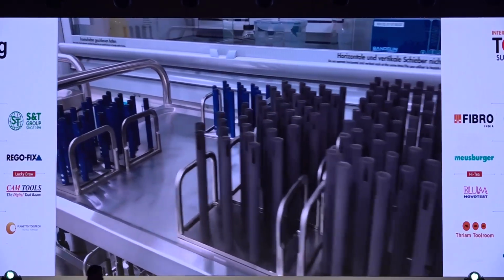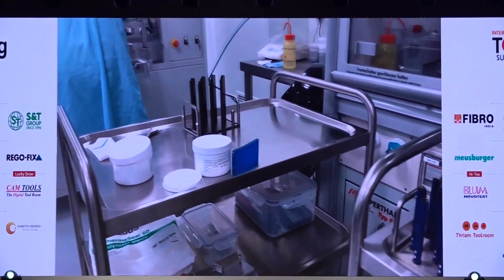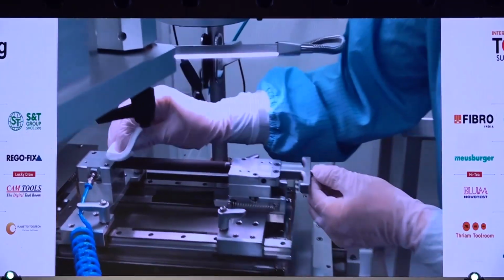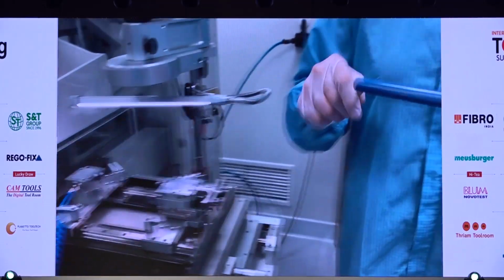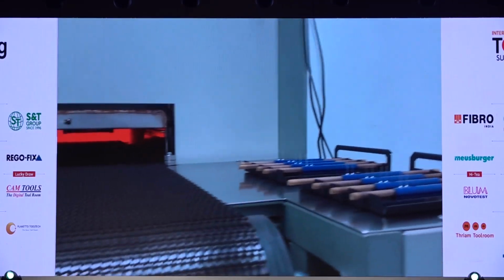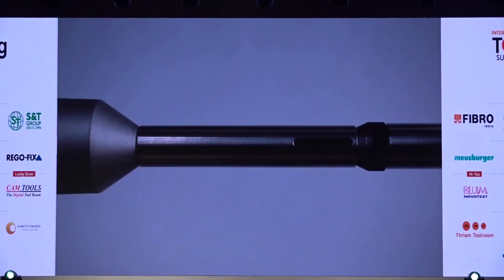And then we clean the steel tube, bring on this steel tube an insulation layer in blue color. And then on the screen printer, we print on the heater layer with the dimensions. And finally, it goes to an oven and we burn out the ceramic at the temperature of 850 degrees centigrade. This is also a patented USP from us for you. Here you see the different layers in small situation.